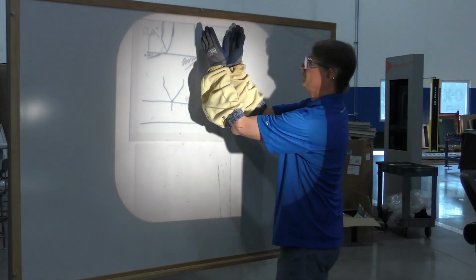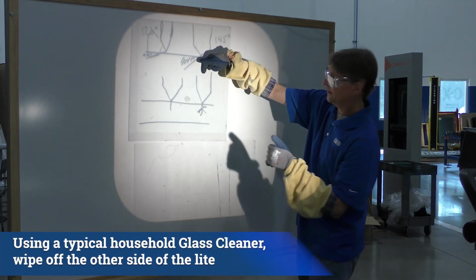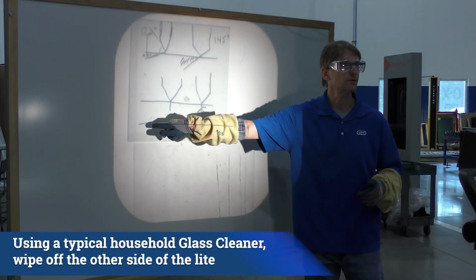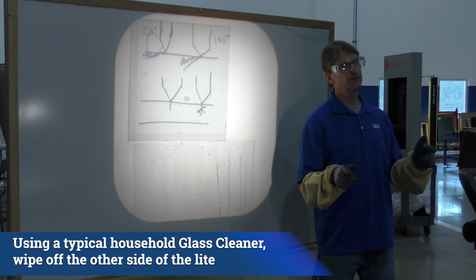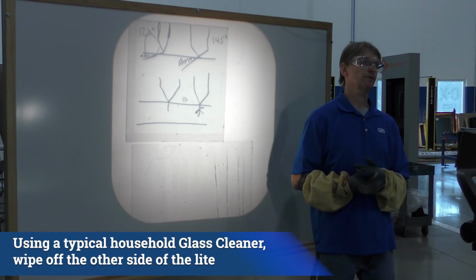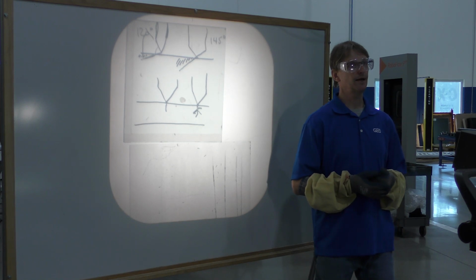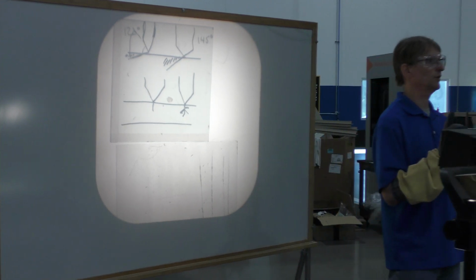So if you have this in mind, see this little hatched area versus this, and you imagine what's happening here. So what's happening is I'm driving the energy down into the glass, but it's shooting out the sides. And for a more blunt wheel, it's driving more of that energy straight down instead of out. That's why I need a more blunt wheel for thicker glass, because I need to drive down deeper, okay? It's counterintuitive, it's the opposite of what you think.